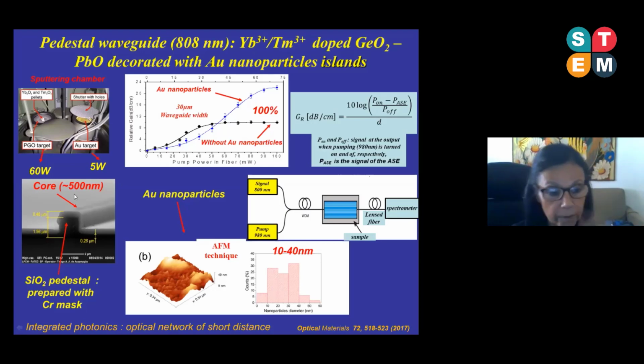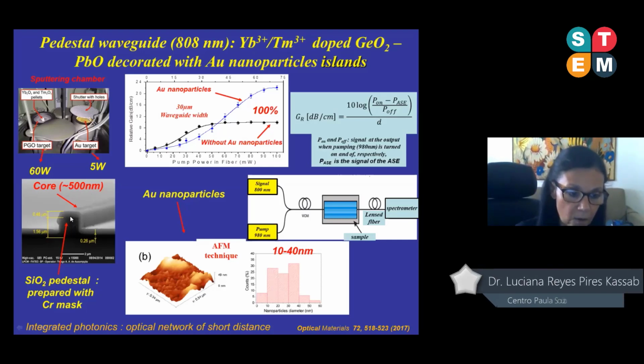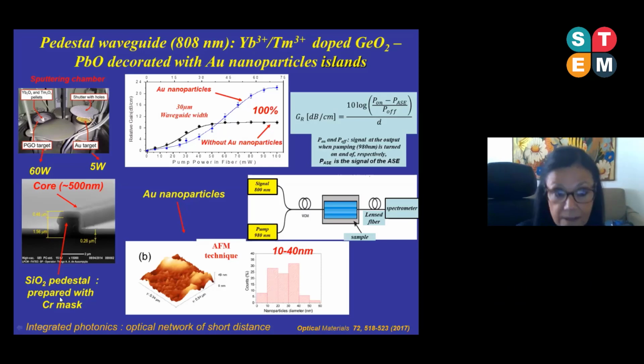In this figure, I show you the core of the waveguide with a height of about 500 nanometers, the silicon dioxide pedestal with a height of about 1.5 micrometers. I'd like to highlight that in this case, the pedestal was prepared with the chromium mask, so using the steps I showed before. And here are the results of the relative gain again at 808 nanometers. We observe an enhancement of about 100% for a waveguide width of 30 micrometers, attributed to the presence of islands of gold nanoparticles with diameter ranging from 10 to 40 nanometers. This result was obtained again by an atomic force microscope.